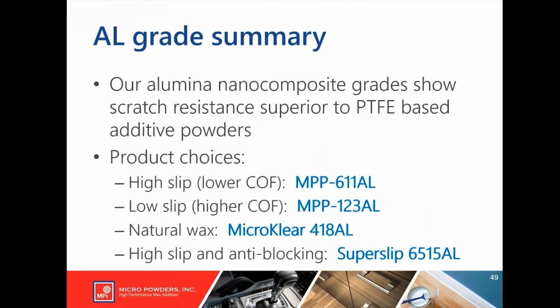So summarizing the AL grades, we show scratch resistance superior to, in most cases, or at least equal to their PTFE-based counterparts. And there's different product choices depending if you want a high slip surface, a low slip surface, if natural wax content's important to you, if you want anti-blocking, if you want those surface haptic effects. So depending on what kind of coating you're working on, we can recommend the best choice in the AL additives family.